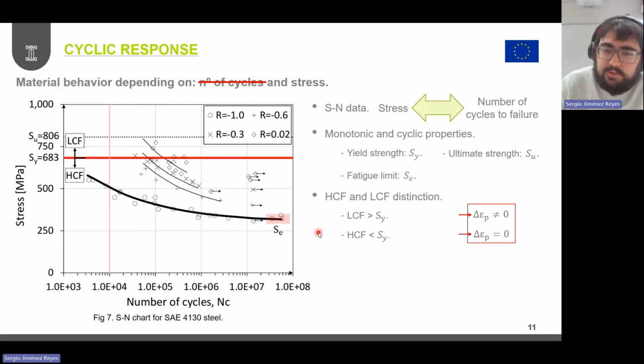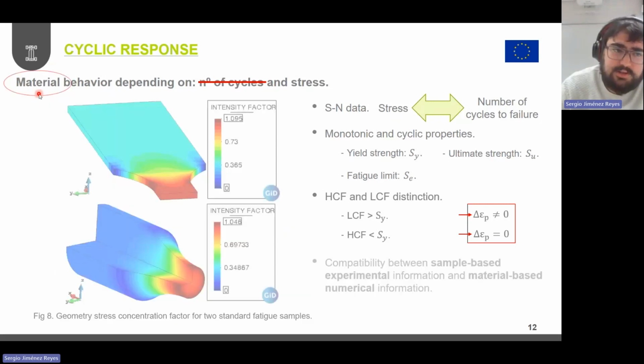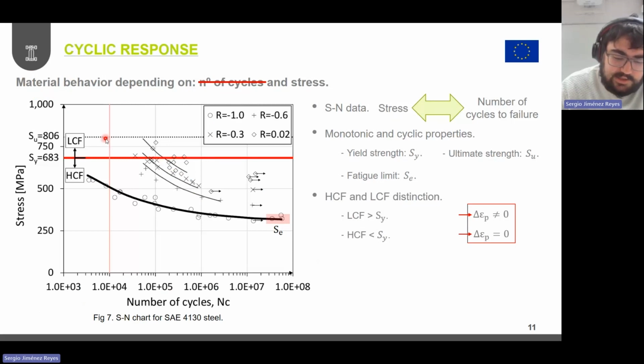So this means that from now on, while I will be describing the high cycle fatigue model, I will be just focusing on those scenarios where the stress state being applied on the material will be just below the yield strength of that material. And considering the fact that I will be presenting a constitutive law, I really want to point out the importance of describing the material behavior and not anything else. And I'm saying this because this type of S-N information usually refers to mean stress, so engineering stress at the sample level, and failure of the sample, and not initiation of the crack or maximum stress at the sample and so on. And this type of information is really important to be taken into account while characterizing the constitutive model that I will then be proposing.